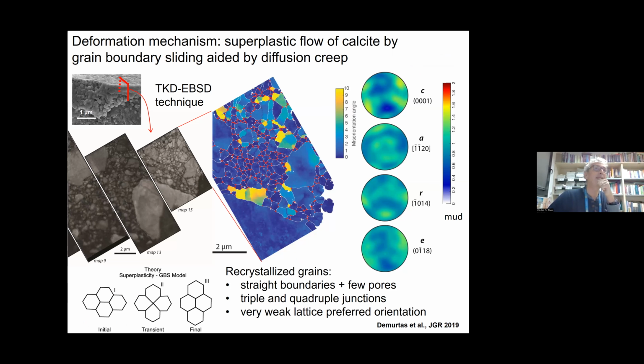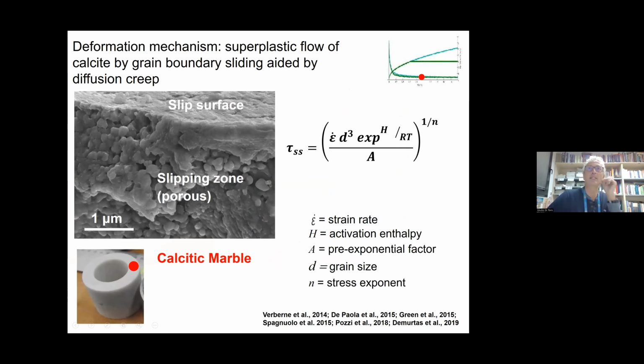And this grain size reduction is something you can observe, especially below the slip zone. Again, the scale bar is 1 micron. We did several studies here. We want to understand what are the processes associated with such a low resistance. And probably it's a mixed process between grain boundary sliding and diffusion creep. These are microphysical deformation mechanisms. I don't want to spend too much time on this, just to tell you how complex nature is, depending on rock type. And what is nice is that there are some constitutive laws that come from other kinds of experiments where you can put together what is the expected flow stress or shear strength of this material at a given strain rate.